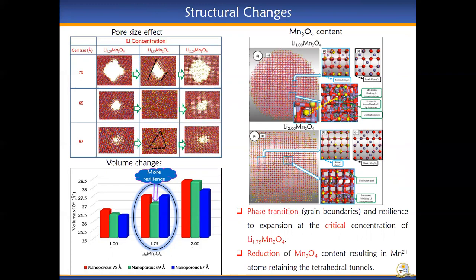Note that the structures undergo a phase transition at the critical concentration of Li1.75 from cubic to tetragonal spinel phase.